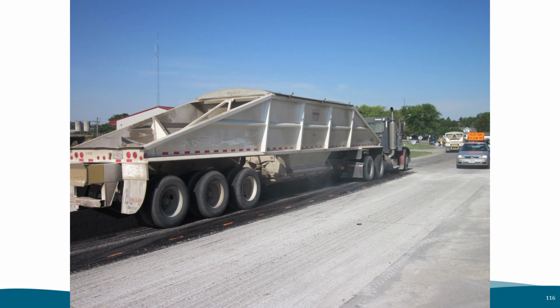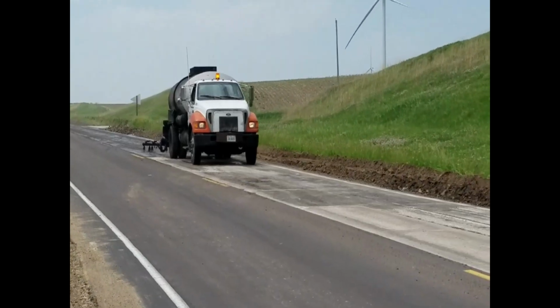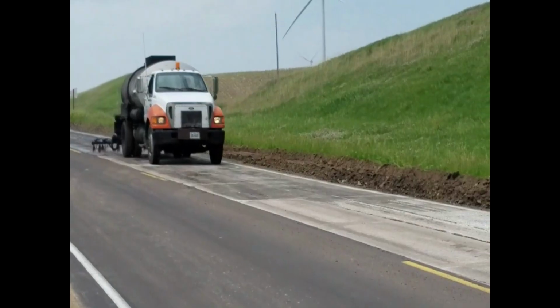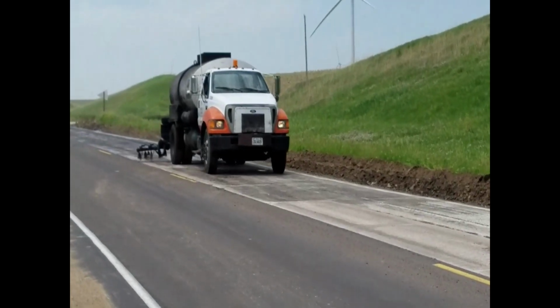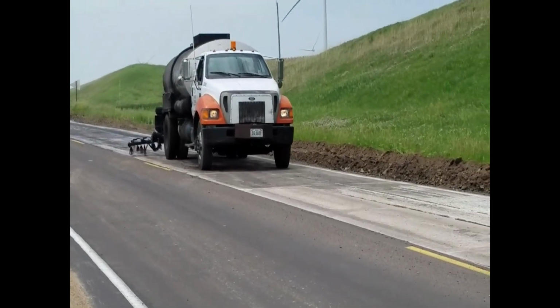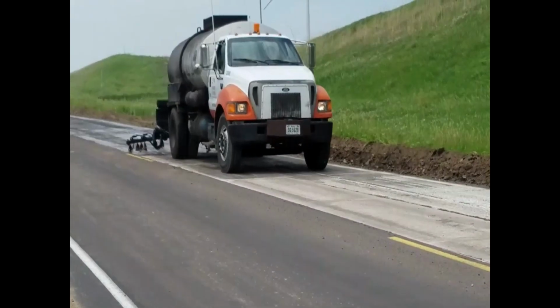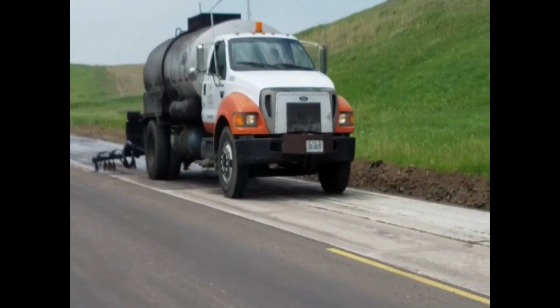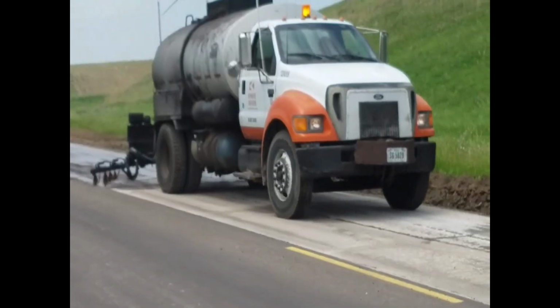Once the surface is milled and broomed clean, a tack coat is sprayed. Here are a couple short videos showing how the tack truck applies the tack, which is called an emulsion. It is basically half water, half oil, and emulsified together with soap to get the oil and water to blend. After the pavement is thoroughly cleaned, the tack truck shoots emulsion on the pavement, giving full coverage, so we get a nice surface for the asphalt pavement to adhere to.